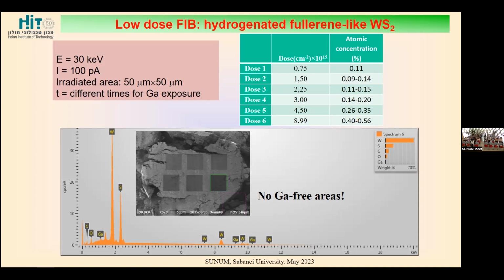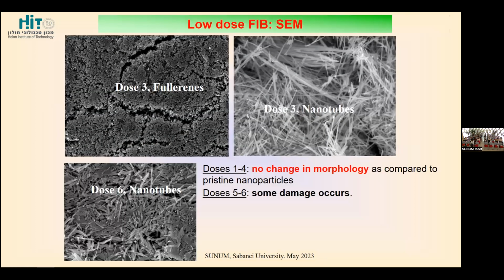And surprisingly for us, we got this atomic percentage of gallium. The weight percent is about the same. It seems not very high, but for implantation these are quite good results. What was most important, it was very homogeneous, so there were no gallium-free areas as detected by EDS. And the structure was nearly perfect, so there were no changes in the structure, unlike with higher ion doses.